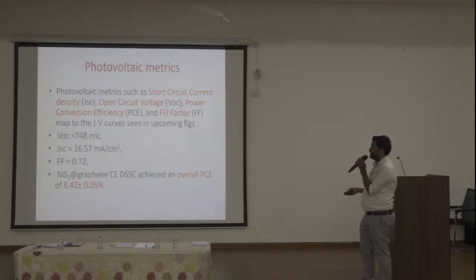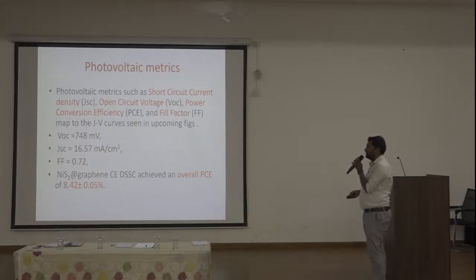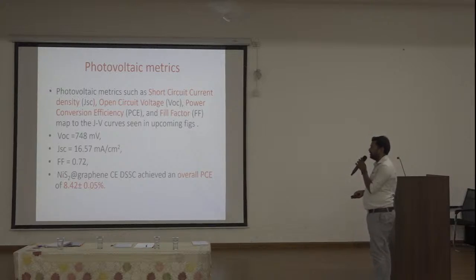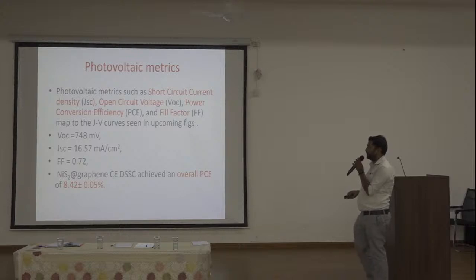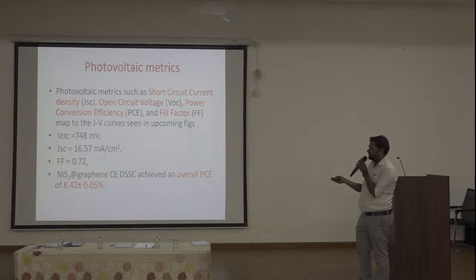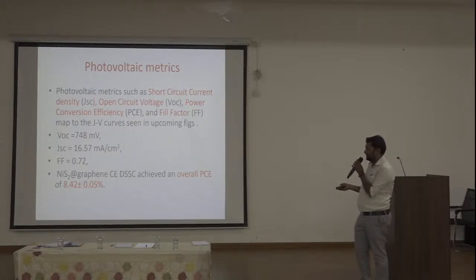So some parameter values are mentioned here, the photovoltaic metrics: VOC, JSC and FF. The short circuit current density, the open circuit voltage, the power conversion efficiency and the fill factor. These are the values of nickel disulfide with the graphene. The open circuit voltage is 748 millivolt, the short circuit current density is 16.57 milliamps per centimeter square, and the fill factor is 0.72. So the overall efficiency of nickel disulfide with graphene is 8.42 plus or minus 0.05%.